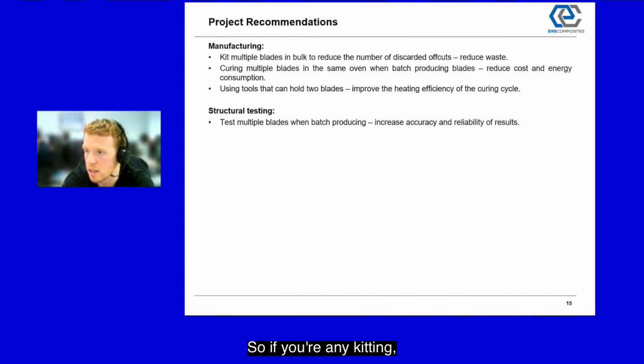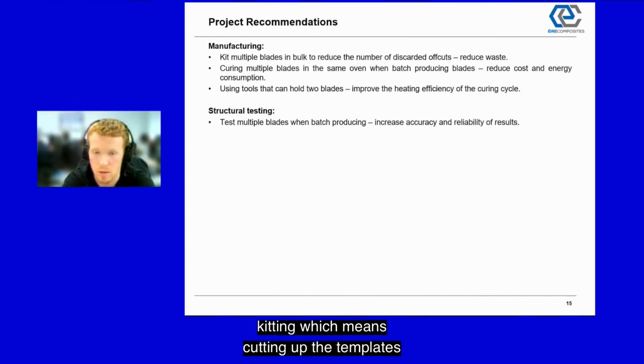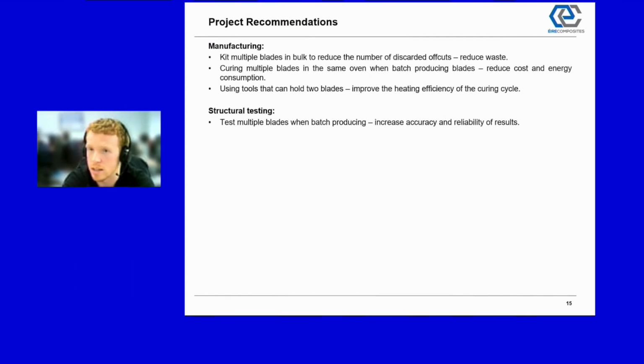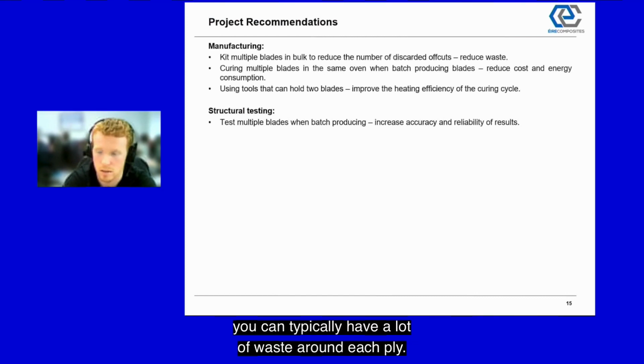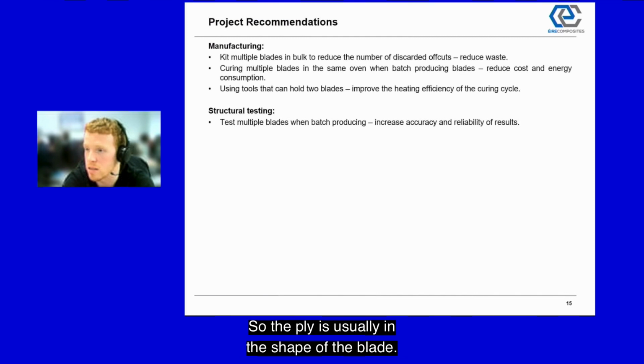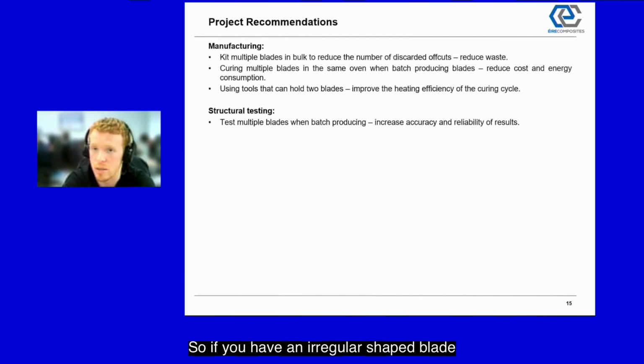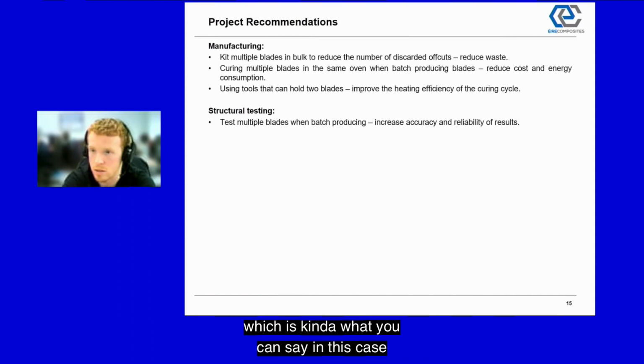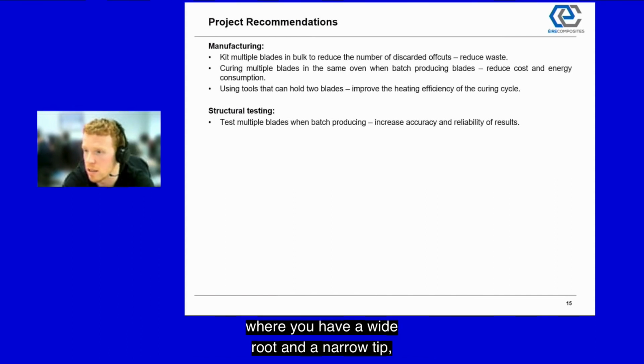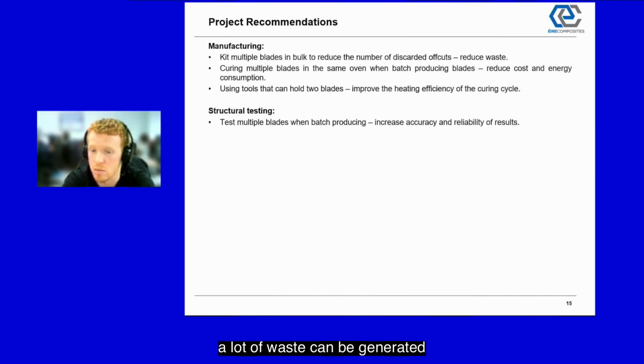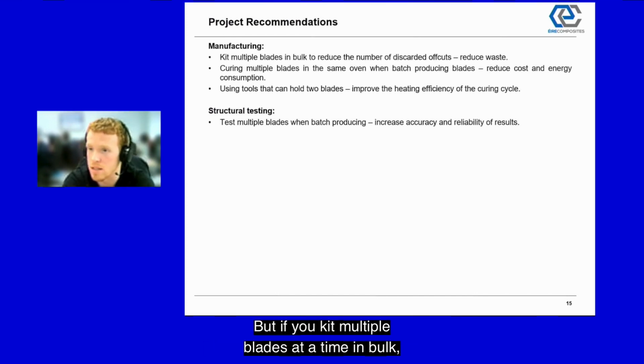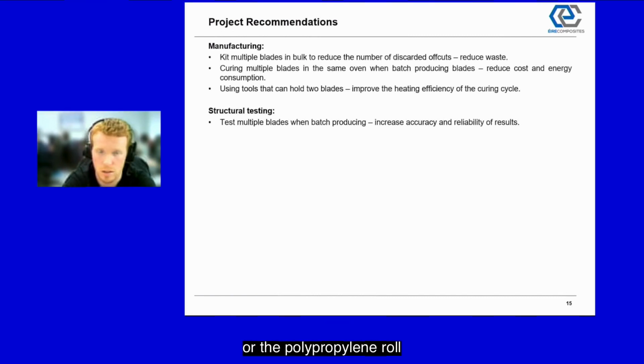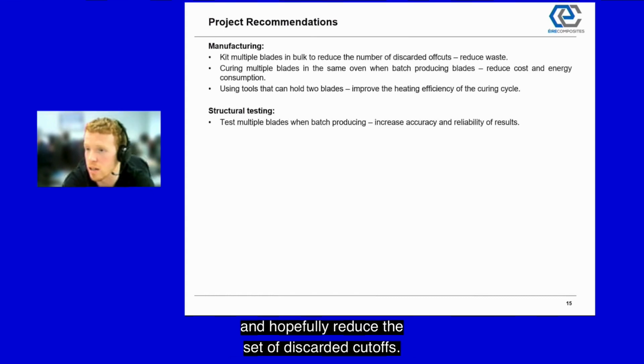discarded offcuts. So kitting means cutting up the templates or the plies that you're going to place into the mold. If you only do one at a time, you can typically have a lot of waste around each ply. The ply is usually in the shape of the blade. So if you have an irregular shaped blade, which is the case here, where you have a wide root and a narrow tip, a lot of waste can be generated just from kitting one blade at a time. But if you kit multiple blades at a time in bulk, you can fit a lot of them side by side along the glass fiber, the polypropylene roll, and hopefully reduce discarded cutoffs.